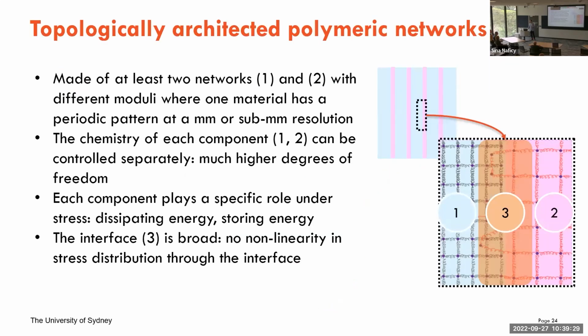So what are these? These are very similar to conventional composites that we see. They're made of two different materials. One is a bit stiffer than the other one, very similar to conventional composites. And one of them, the reinforcing phase, has a periodic pattern. As you can see, these are aligned in one direction, for instance, very similar to some composites as well. There are two differences, or actually three. One is that these are all made of very soft material, unlike most conventional composites that we know. Two is that the resolution of these patterns is at sub-millimeter or millimeter level. So these gaps are actually 1 millimeter or a few hundreds of microns.